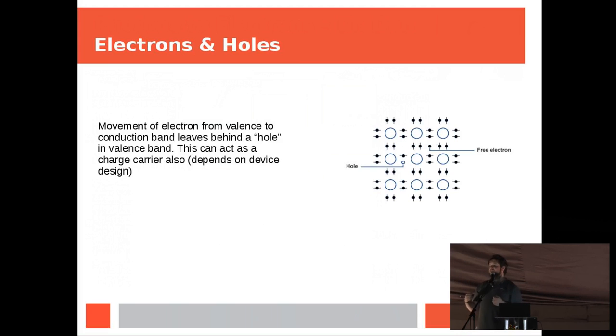Crucial to this is the concept of holes. So to think like this, you have to kind of think of two diagrams at once. You have to think of energy, a diagram with energy going up the scale, and then a separate diagram with space. If I move an electron from underneath that gap to over the gap using energy, I've left behind a hole. And that is the technical term, a hole. And if this electron moves around a bit in space, but at that high energy, it's moved away from where the hole was. And the hole now looks like a separate entity. And it turns out that statistically, you can treat these holes just as particles. We call charge, which is carried by free electrons in the conduction band, and charge, which is carried by free holes in the valence band.